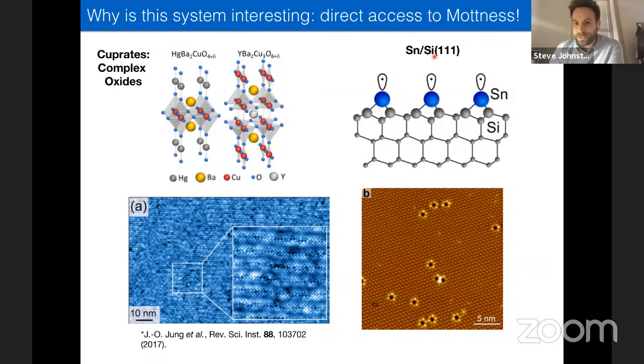In this system, the tip gets direct access to where the superconductivity occurs. You don't have to tunnel through anything to get there, and you can grow it in very large, clean surfaces. So one of the things I'm really excited about is that this system offers us a really unique opportunity to look at the fundamental physics of single band Hubbard models, without any of the oxide complications that we get in cuprates. One of the things we're currently thinking about is whether there are substrates we can do this on where you'll get a square lattice instead of a triangular lattice, for example, and trying to get at Hubbard physics that way. I'm hoping we'll find a system soon, and I'll be able to come back and tell you a bit more about that.